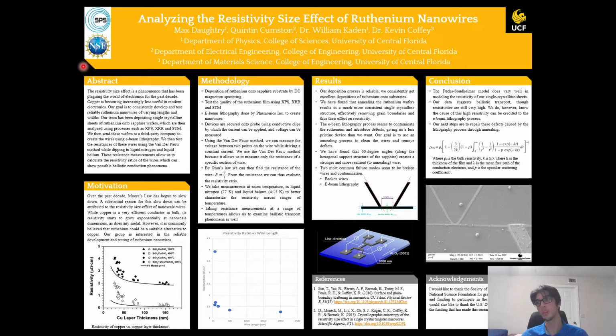And on top of that, we're also looking for ballistic transport, which I'll talk about later. Basically, the process of creating these ruthenium nanowires starts with a deposition of ruthenium onto sapphire substrate by DC magnetron sputtering. We then test the quality of these depositions using characterization techniques like XPS, XRR, and STM. So X-ray photoelectron spectroscopy, X-ray reflectivity, and STM, or scanning tunneling microscopy. And alongside this, we also send off some of the wafers, or some of the depositions, to a third-party contractor, Plasmonics Inc., where they do e-beam lithography to create our nanowires for us.